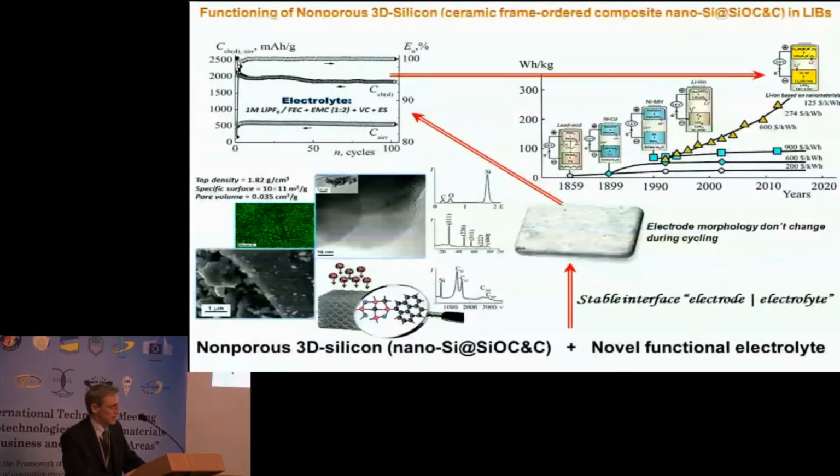which is an integral indicator of irreversible binding of lithium ions in the electrode surface and in its bulk in N cycles. We identified the principal role of a natural oxide layer with silanol groups on the silicon surface, and the mechanism of reactions with its participation in the formation of the passivation layer. In addition, we were the first to use fluoroethylene carbonate-based electrolytes instead of ethylene carbonate.